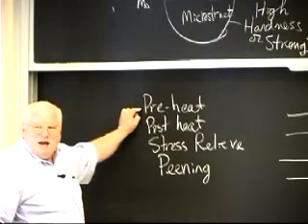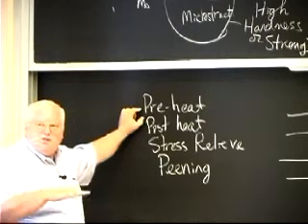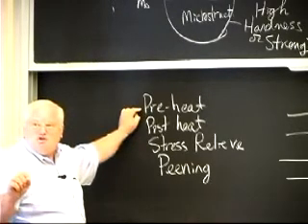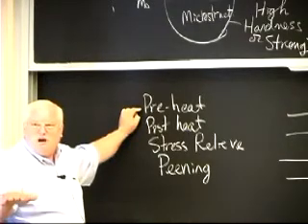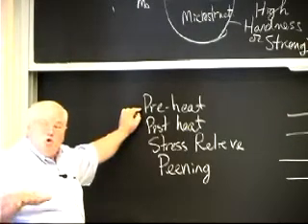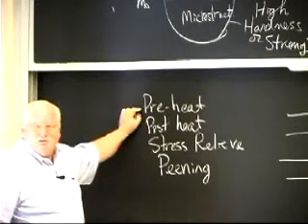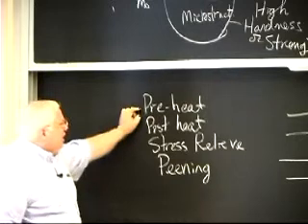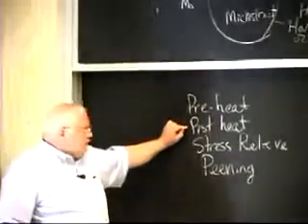Now the reason for that is that when steel gets down below 50 degrees Fahrenheit, you can start to form dew, condensation on it, while you're welding it. You may not see moisture, but you could have a layer of moisture that you're welding over, condensation on the surface. Or if you get below 32, you actually get frost on the steel. You shouldn't weld over frost, not a good idea. Okay? Frost contains moisture. You can post-heat the steel to slow the cooling rate down even more.